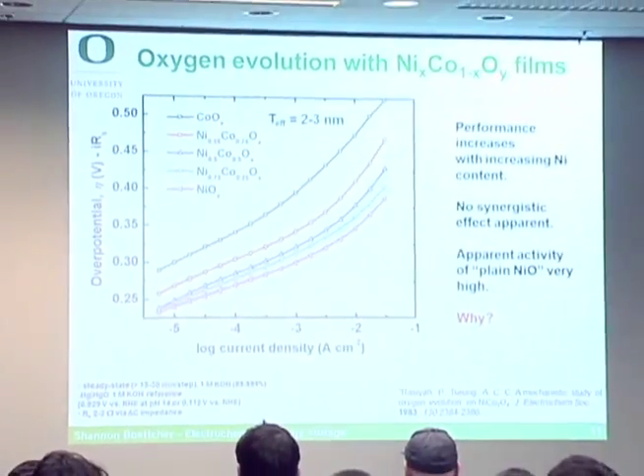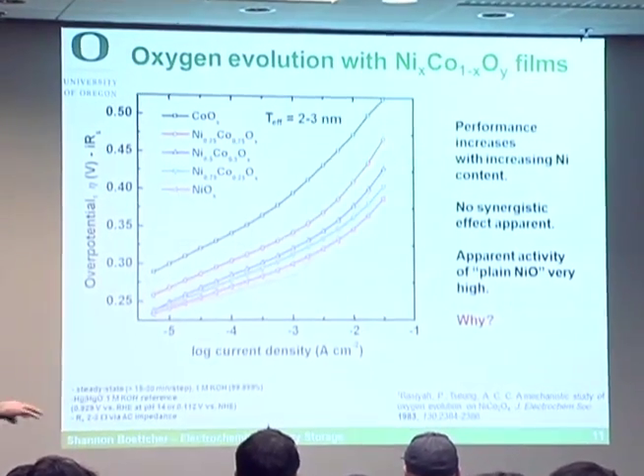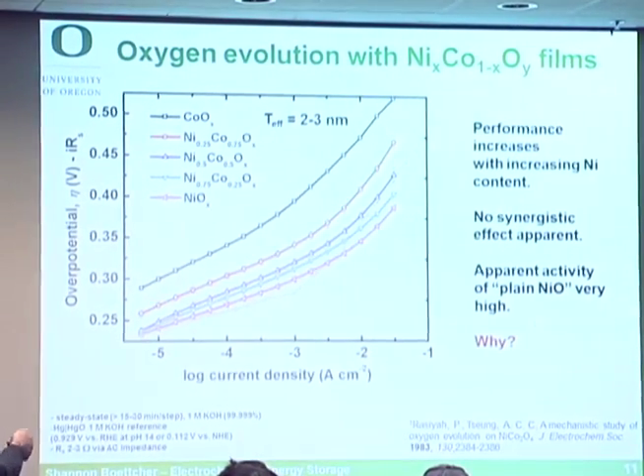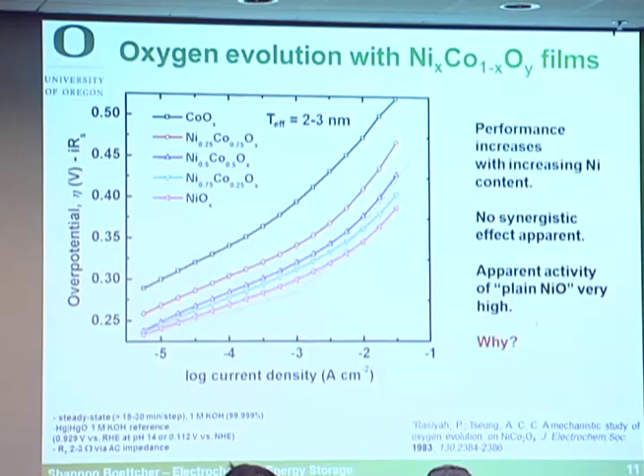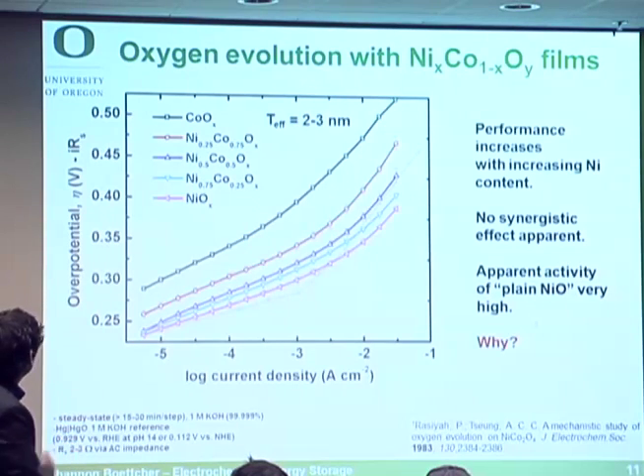So we made these thin nanocrystalline films. They're only a few nanometers thick, 2 or 3 nanometers effective thickness, so there's some roughness, and they're a little bit nanocrystalline, but they're thin films on gold electrodes on these quartz crystal microbalances. And we found that cobalt oxide had the worst performance, nickel oxide had the best performance, and there was a linear trend as we added nickel to cobalt.